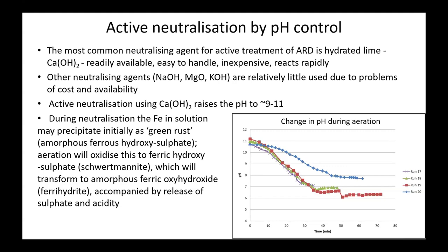Initially, it'll be a sulfate, ferric hydroxysulfate, which is a mineral called schwertmannite. And then that will eventually, over time, lose its sulfate and also lose some H+ and transform to a ferrihydrite, ferric oxyhydroxide. And with time, now we're talking years, that will transform to a crystalline iron oxide mineral like goethite. Just on the right there, you can see that change as you lose the sulfate from the initial precipitate and transform it to just an oxyhydroxide, the H+ that's released at the same time will drop the pH. So that is something that needs to be kept in mind sometimes. Next slide.